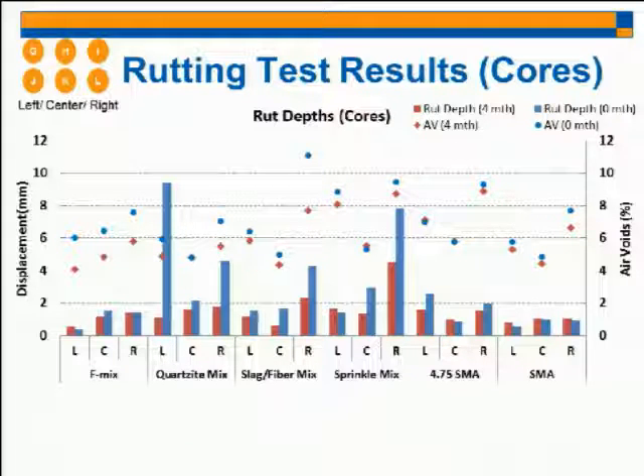And also we did the rutting test using the field cores. Here, F mix, Quartzite mix, and L means that this is one lane. We took 6 cores from one lane. This is the left wheel path, the center of the lane, and the right wheel path. As you can see, the rutting performance is very sensitive to air void. So we measured the air void of these cores before we did the rutting test. As you can see, the right wheel path always provides the higher air void because when we place the materials in the field and then compact, the right side is unconfined. So when you apply the same number of passes, the right side of the lane always has the higher air void.